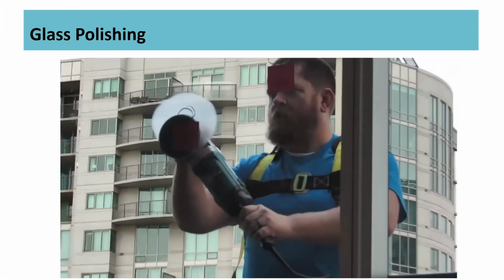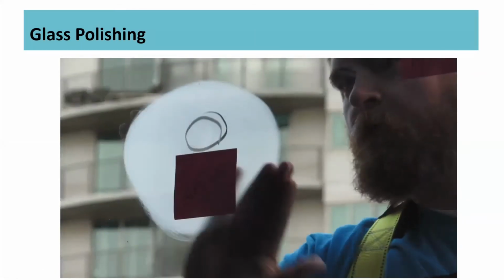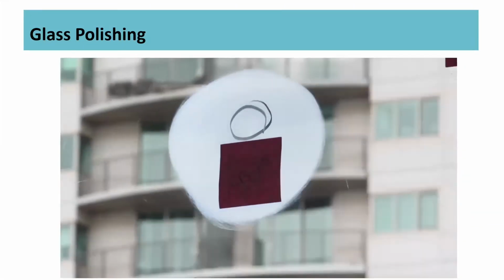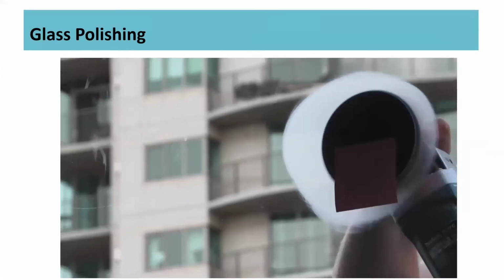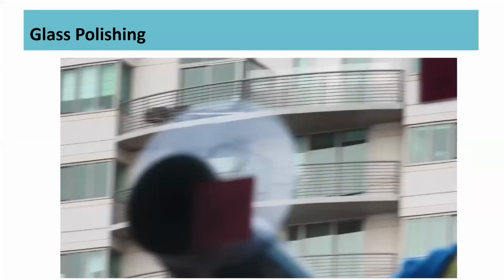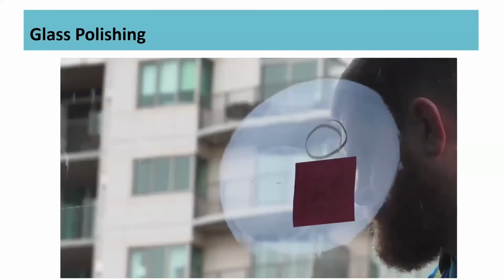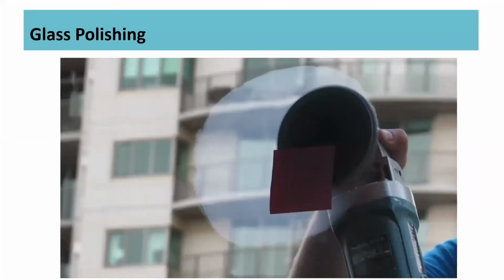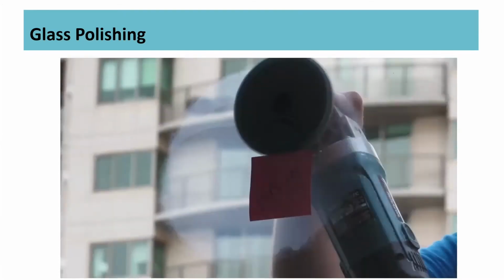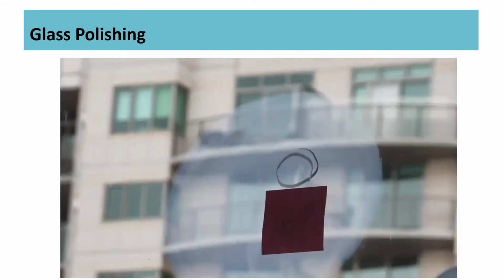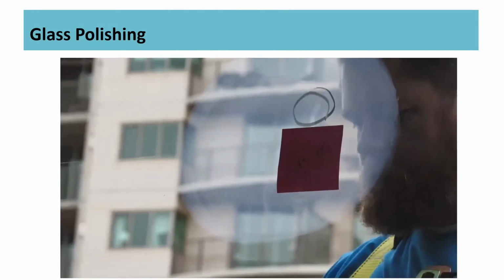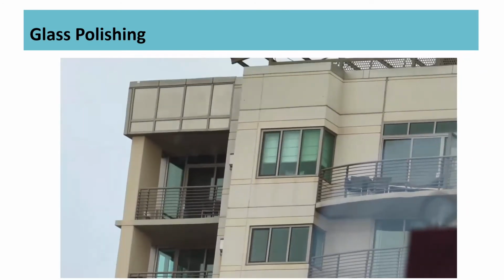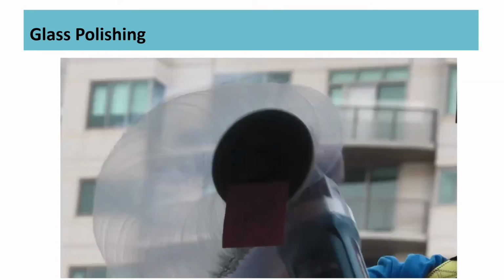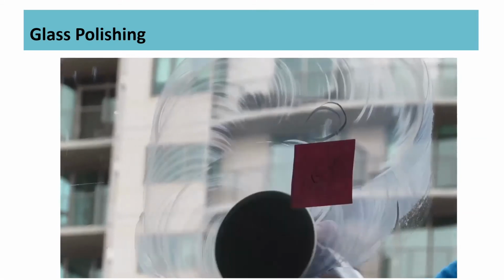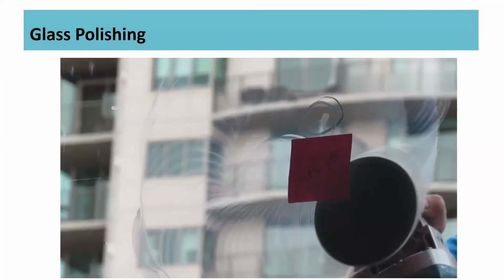Okay, here we go. Sorry about the mix up there, but you can see the operator here is starting out with a rough sanding disc, and he's roughening up the area and will proceed with feathering out to the adjacent areas. What Stephen and I have recently witnessed on a project out west that we're just finishing up is that this process is very workmanship critical. It looks like this operator could do this in his sleep, but if that polisher is not held flat against the glass surface, you can develop some ridges and areas of distortion that will be nearly impossible to get out.